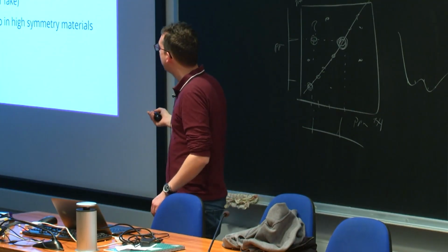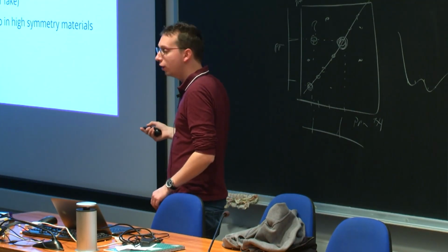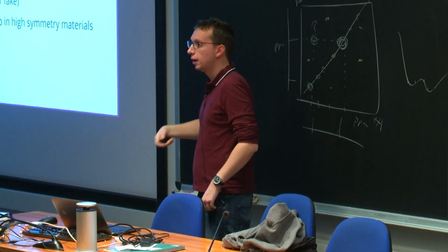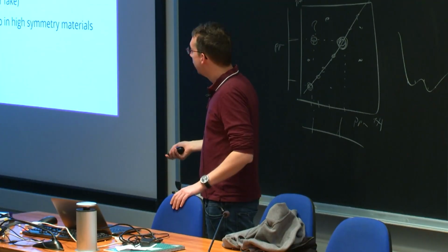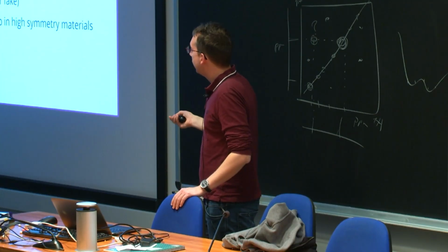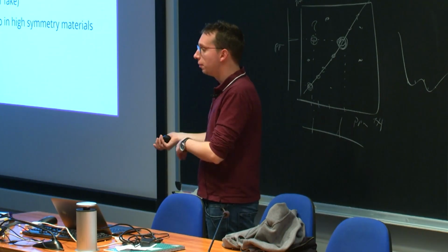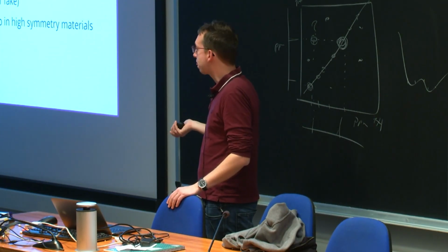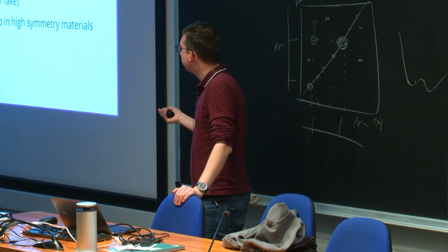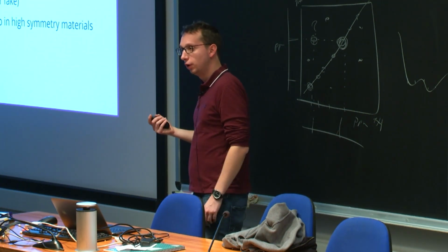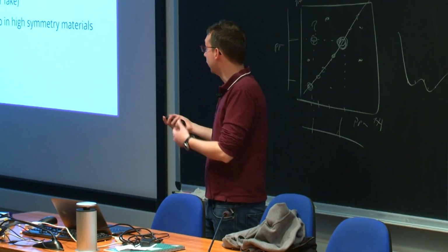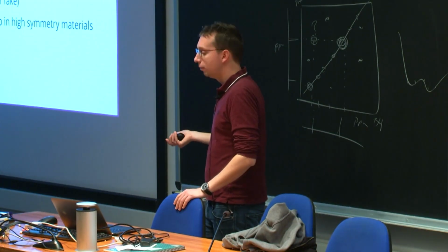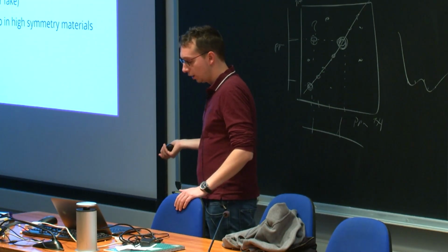So computing the effective charge is cheap. On top of the phonon calculation, you only need to do a sum of the wave function, which is something you do many times during the self-consistency cycle. And as before, they can also be computed for metals, either real metals or fake metals. The code doesn't care. It doesn't stop you from computing them. They are normally zero in high symmetry materials, which is also interesting to test, like if they are exactly zero or not exactly zero. It can be a good hint if your calculation is properly converged.